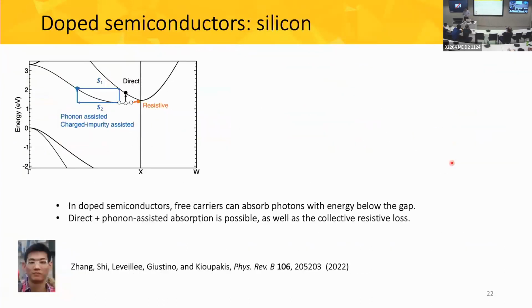All right, so I'd now like to discuss what happens once you introduce dopants in a semiconductor. So if your semiconductor does not have free carriers, light can only be absorbed when its energy is above the band gap, in order to be able to excite an electron from the valence to the conduction band. But when you have a doped semiconductor, you have some extra electrons at the bottom of the band, which can also absorb light. And they can absorb light in a direct fashion, like by going to the next band. They can absorb light assisted by a phonon, or they can also absorb light in a resistive process where they behave like they respond to the oscillating electric field, like the way conducting electrons do in a metal.